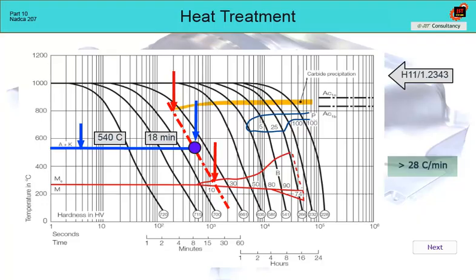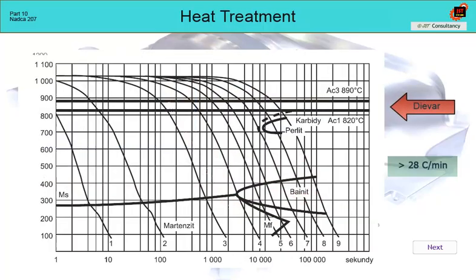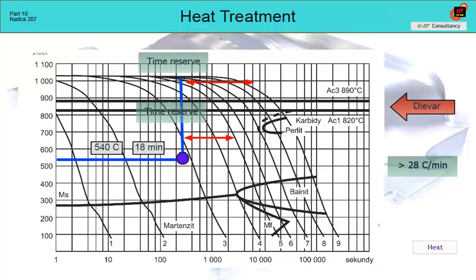But we see a different picture on the CCT diagram for Dievar. The critical cooling rate shows that to exclude bainite from the structure, it is possible to cool almost 3 times slower than for material H11, and to exclude precipitation of carbides then almost 40 times.